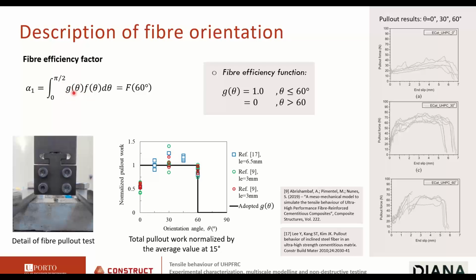So which function should we use then? We adopted the simplest one. For sure there are better proposals than this one, but this has the advantage that it is very simple. What are we considering? The fibers are effective if the orientation angle is smaller than 60 degrees. If it's larger than 60 degrees, we say that they're not effective, so we will not consider them.